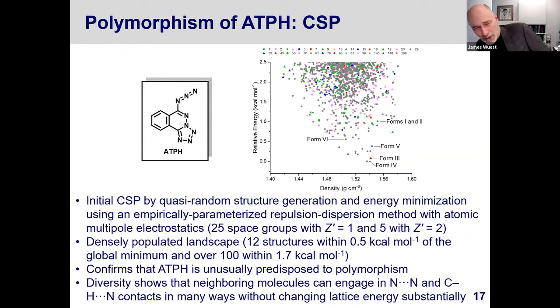So we wanted to look at this more carefully to see if our intuition as structural chemists was supported by theory, by crystal structure prediction. So Graham Day and his group have taken a look at ATPH, and this is the same plot showing the potential crystal structures that I showed you early in my talk today. So again, there are over 100 possibilities within 1.7 kilocalories per mole of the global minimum, and there are 12 different possibilities that lie within 0.5 kilocalories per mole of the relative energy.